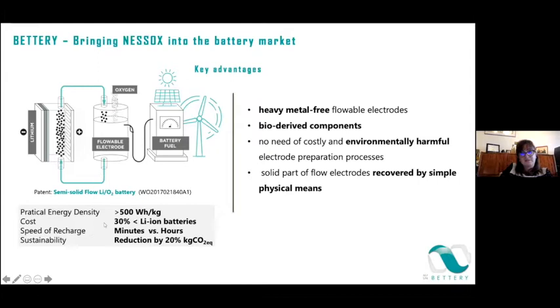And also the system we demonstrate is pretty sustainable, and we can reduce the carbon footprint of its production. Indeed, we don't use heavy metal, and we can exploit biochar for the carbon present in the slurry. And also, given that this electrode is a liquid, we do not need costly, environmentally harmful electrode preparation processes. At the end of life, the solid part of the slurry can be recovered and recycled by simple physical means.